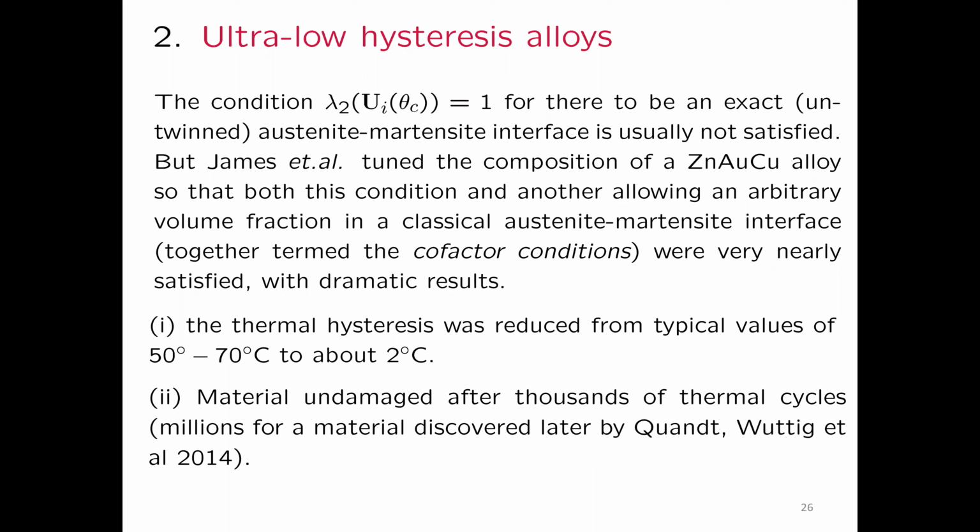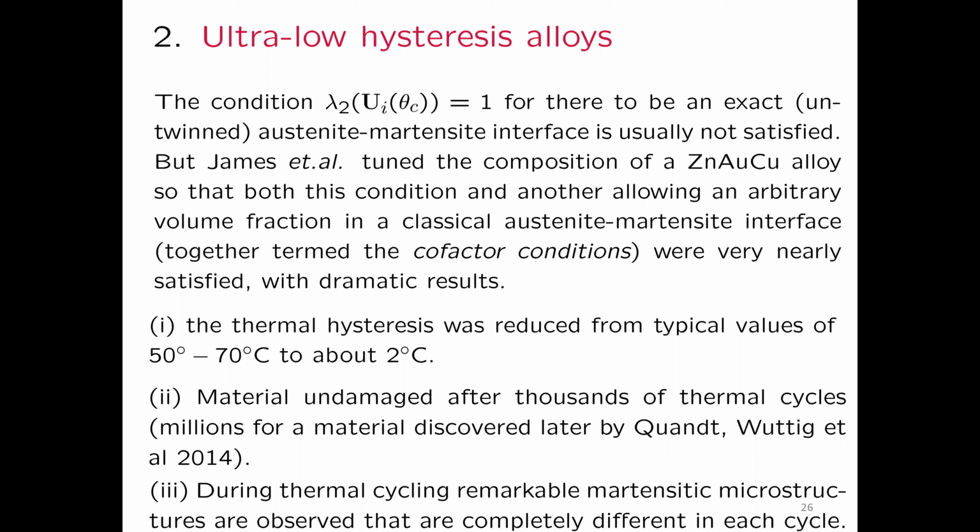And the material is undamaged after thousands of thermal cycles, in fact, millions for materials that were later discovered. And furthermore, during the thermal cycling, remarkable microstructures appear that are completely different in every cycle. So I'll show you a movie of this.